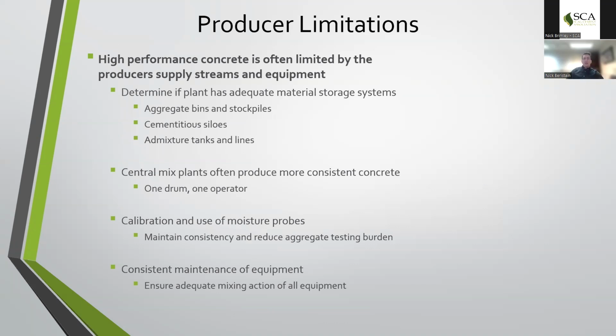Some of the limitations we often encounter in these sorts of production processes, especially with high performance concrete, is a mechanical limitation. Like I mentioned earlier, do we have adequate material storage systems, whether that be aggregate, cementitious, or admixture tanks and lines? Some become or are lesser known, particularly if you're using siloed silica fume. You need a slightly different setup to make sure you're not having issues moving the silica fume throughout your plant.